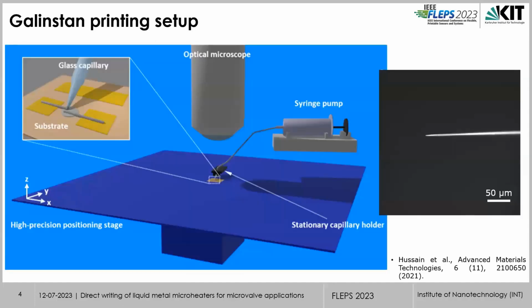So we know the ink, but there are certain problems with the writing of liquid metals. They have high surface tension, and also there is a gallium oxide layer present on top of these liquid metals. The combination of all of these makes it hard to be printed with inkjet systems or other direct writing methods. So we made this setup.